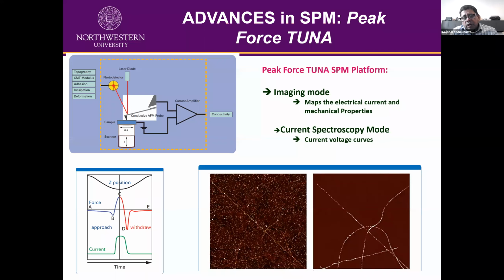And when you see that topography, you can image both nanoparticles and carbon nanotubes. The carbon nanotubes have electrodes on them and the nanoparticles don't. So when you apply an electrical bias, you can see in the Peak Force TUNA image on the right, you can image those carbon nanotubes. Obviously, some nanoparticles are on these carbon nanotubes. So you can see a pretty high current.